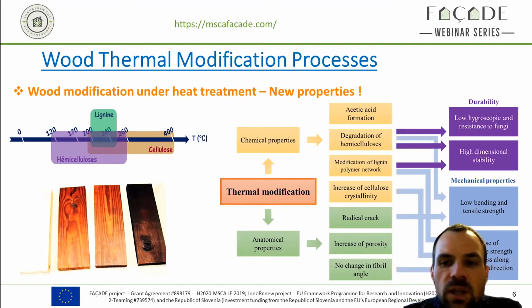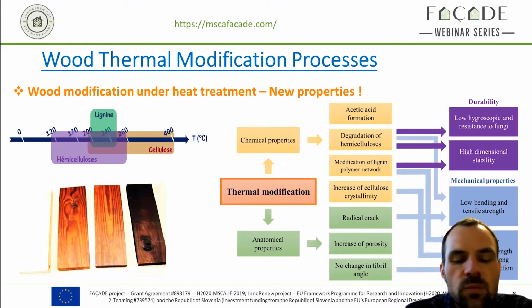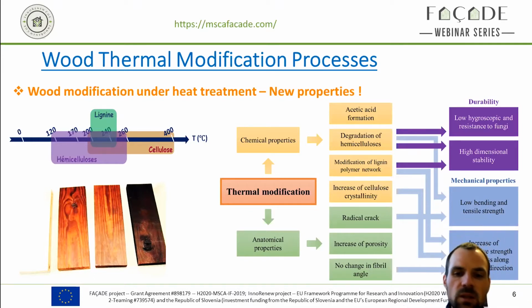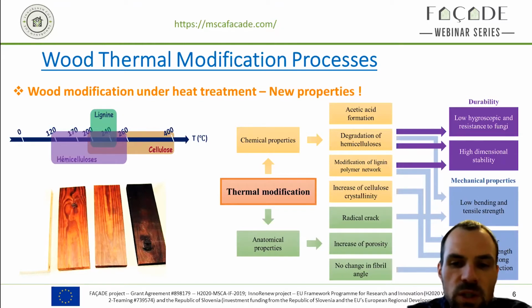All of these modifications provide the heat-treated wood new technological properties, such as a better durability with improved hydrophobicity and decay resistance. We can also observe higher dimensional stability. Concerning the mechanical properties, we can observe that heat-treated wood presents lower bending and tensile strength properties, but we can also observe an increase of the compressive strength and stiffness along the longitudinal direction of heat-treated wood materials.